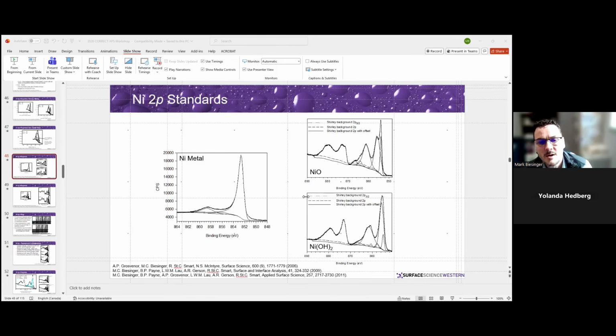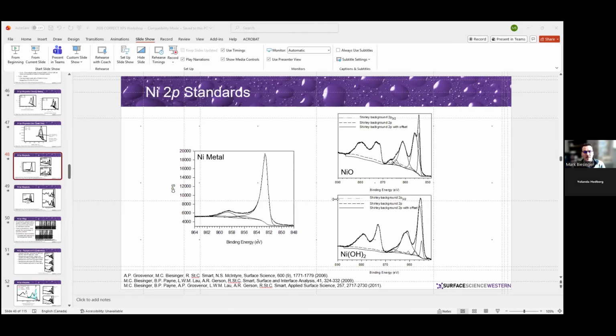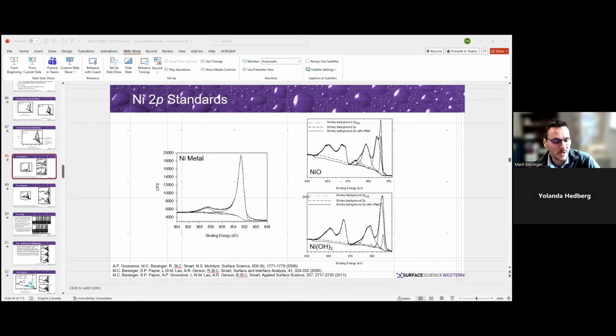Can you please comment on overlapping of Auger peaks of nickel and iron with each other's 2p3 spectra in the NiFe2O4 spectra? How do you quantify properly in such a case of overlaps? On the nickel side of things, it was probably pretty good. I don't think we saw too much overlap. I know in the iron peak, the overlap of the nickel Auger is a little more problematic. The papers from Tony Hughes and Chris Easton recently also discuss how to deal with that. Basically, you can model what that Auger peak contribution should look like underneath the iron 2p peak. So it can be a problem. You've got peak overlaps. The easy way to deal with that is if you have a different X-ray source that you can then use.